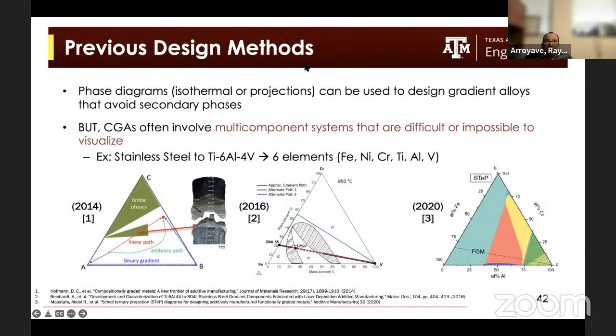There have been some attempts to use computational tools to design these alloys. Most of the time what people have done is to try to predict ternary phase diagrams and then find, by human intuition, a path that may run around obstacles. But the problem is that these approaches are extremely difficult to scale and deploy in the case of multi-component materials. Why? Because humans are not built to see things in more than 3 dimensions. So when you have many more dimensions in your design problem, it is extremely difficult to come up with robust composition paths.